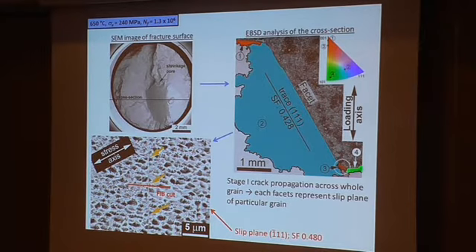We followed a procedure: first fractographic analysis, choosing the cross-section plane which is interesting for us. EBSD analysis was the second step, and as you can see, I chose this area, this small grain, where I found the localization. I hope it's at least a little bit visible. It's highlighted by yellow arrows, this line.